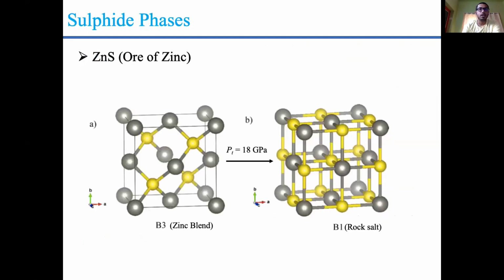First, I want to talk about zinc sulfide phases. Here you can see on the left-hand side the zinc blende structure, and on the right-hand side the rock salt or NaCl structure. Zinc blende has a well-known phase transition from the B3 to the B1 phase at around 18 GPa. But natural ZnS always comes with some impurities like iron, nickel, cobalt, etc. This study aims to investigate the effect of these impurities on the physical and electronic properties of impure ZnS. Thus, I chose Fe as an impurity with variable concentration.